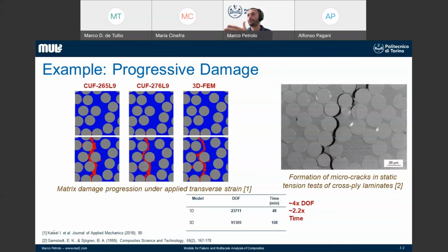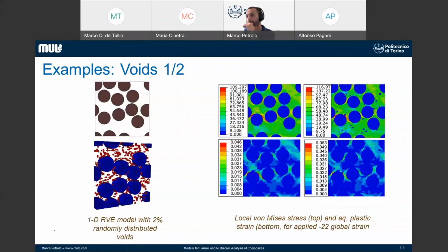For instance, the progressive damage along the micro scale. So the progressive damage we saw before was at the layer level, so along each ply. Now we can get the progression of damage inside the matrix along the fiber. So this is just an example of the depth of results you can get with a micromechanical analysis. Or you can insert defects.